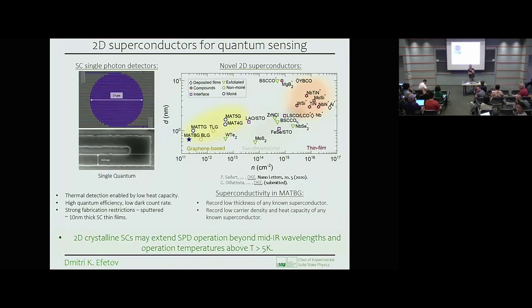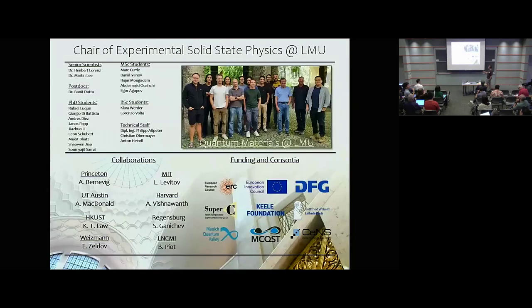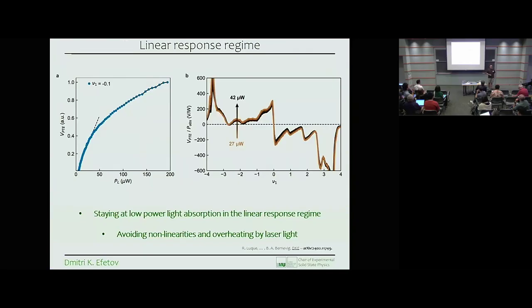So your measurement on this twisted layer, what is the temperature increase with the laser power? Right, this is something which we calibrate quite accurately, so this is an extra slide. This is also in the side of the paper, right? We try to stay very low, because in principle with a laser, you can heat the system by hundreds of Kelvin if you want. And with pulsed lasers, you can go up to 1,000 Kelvin. So here it was important to really reduce the power with which we measure to below 1 Kelvin excitations. So we did some heat capacity estimations of what laser power we stay below that.